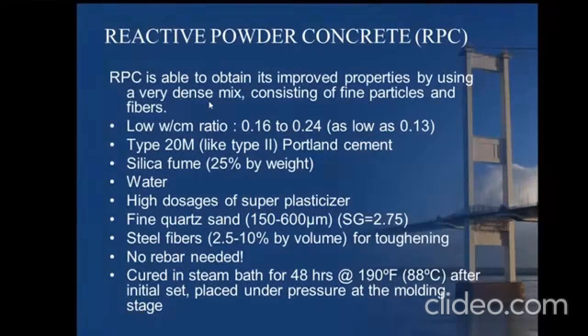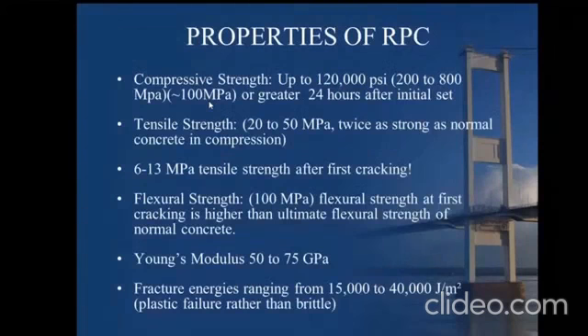I'll just show you some other results with respect to this. So properties. We have achieved, as I told you, 200 to 800 MPa, and in India we have achieved around 100 MPa of this reactive powder concrete. Tensile strength is actually enormous, 20 to 50 MPa. And generally, wherever we are going to use this reactive powder concrete, we don't go for steel reinforcement.